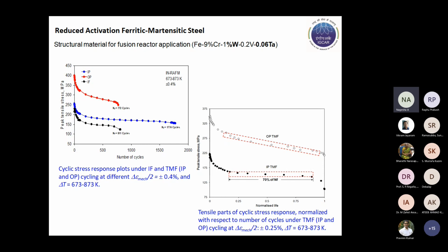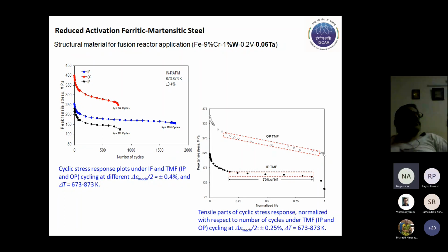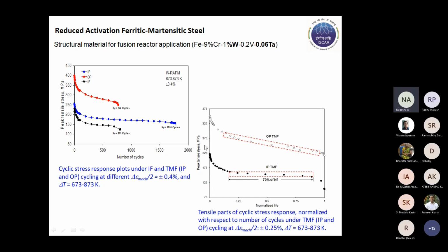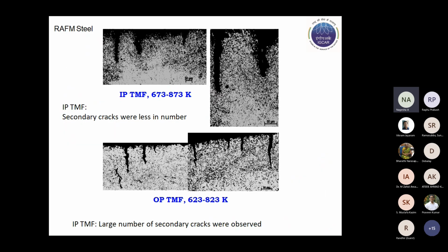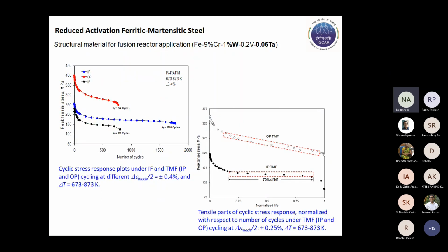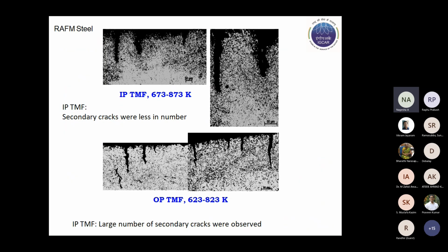As you can see, the out-of-phase TMF leads to lower life compared to both in-phase and isothermal loading, where you can see accelerated softening happening in OP TMF in comparison with both the IP case as well as the isothermal cyclic loading. This is related to, as I will be coming to it a little later, the oxidation-associated damage, which will be seen in the next few slides.